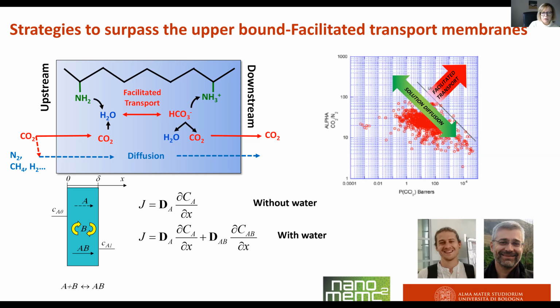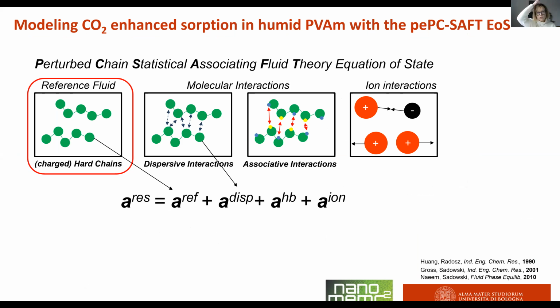You can actually use a thermodynamic model to model the absorption with reaction, and this was carried out in the framework of a European project just concluded, and the model used was the polyelectrolyte SAFT equation of state, and the polymer studied was polyvinyl amine, which is a polyelectrolyte. So this model uses the same scheme valid for the SAFT equation, so associative interactions, dispersive interactions, and so on, plus a term accounting also for the ion interactions.